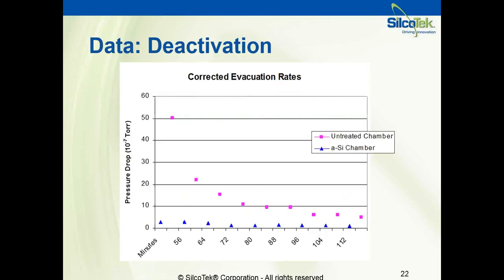Moving over to pump down times, there are lots of issues with stainless steel vacuum chambers, even though that is the substrate of choice for these sorts of components. The pink dots represent the evacuation rate for an untreated stainless steel chamber. To get to 10 times 10 to the minus 7 Torr with an uncoated stainless steel chamber, it takes upwards of an hour and a half or even longer to achieve that rate.